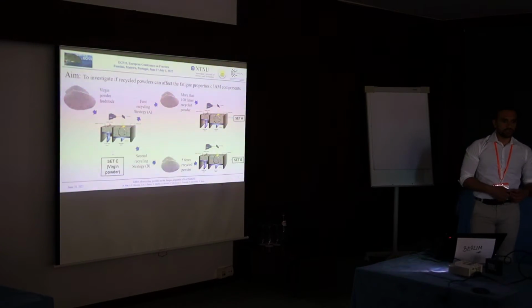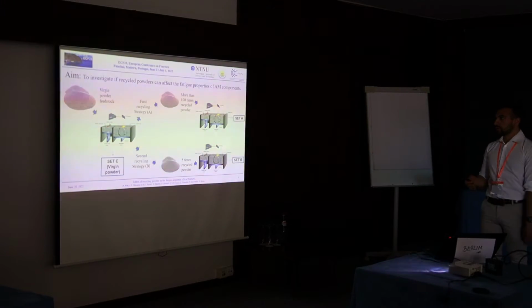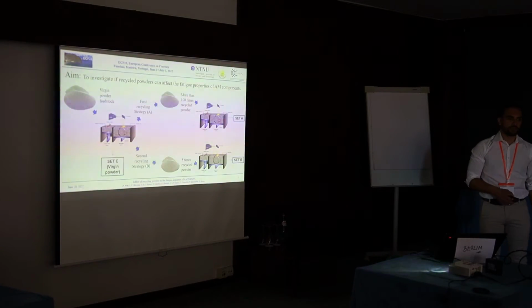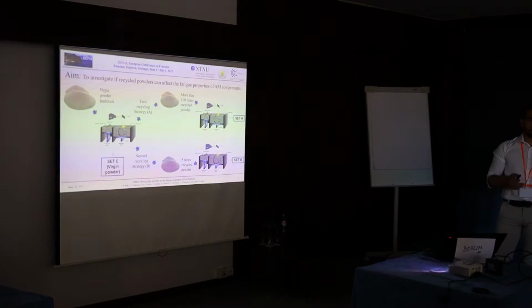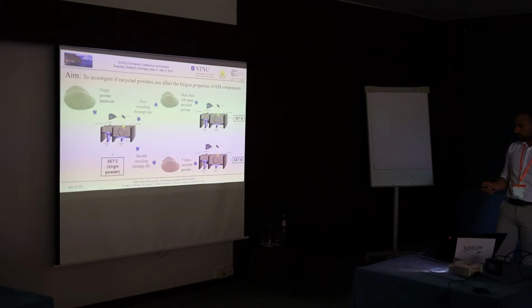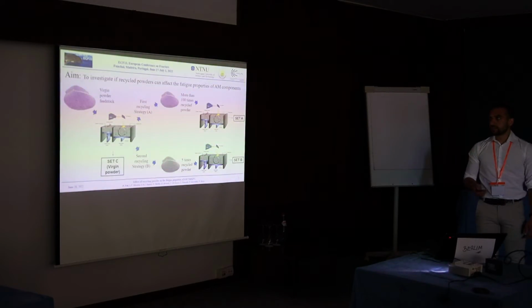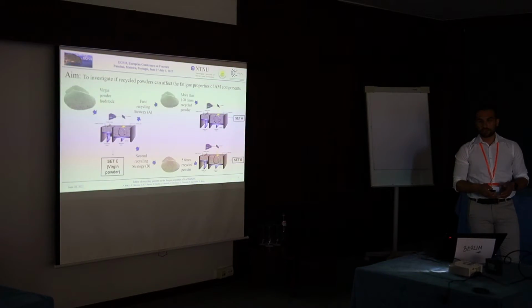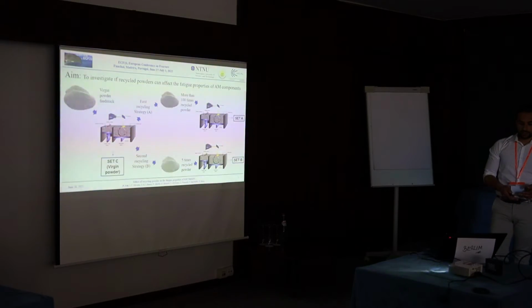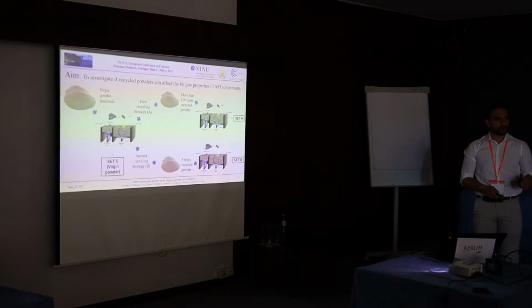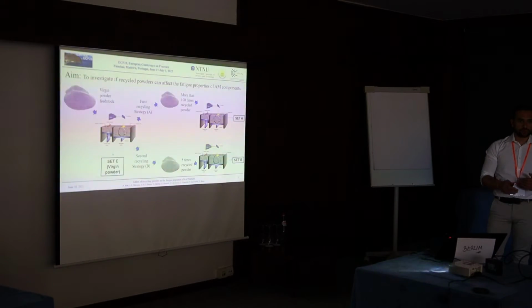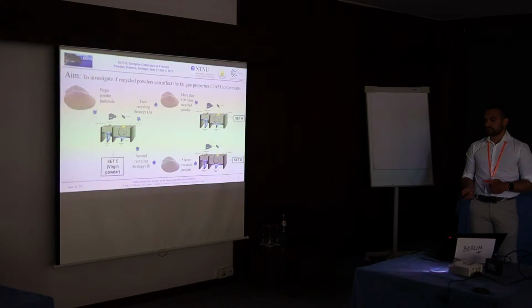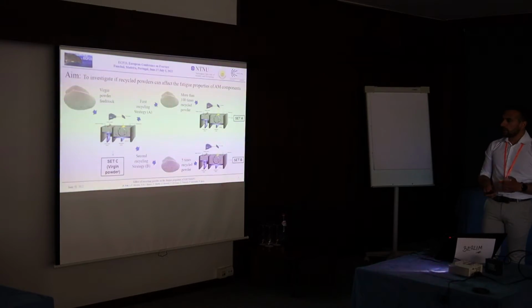First of all, the aim of this particular part of the project was to investigate if the recycled powder can affect the fatigue properties of additive manufacturing components. In order to do this, we considered three different sets of specimens. The first one starting from virgin powder feedstock, and the other two sets were realized starting from powders that were recycled according to two different strategies. The first strategy was to consider powders that were recycled more than 100 times, while the second strategy was to consider powders that were recycled up to 5 times, not more than 5 times.